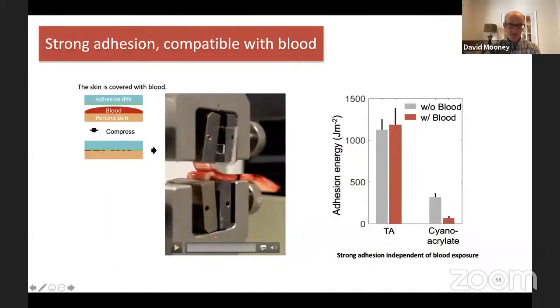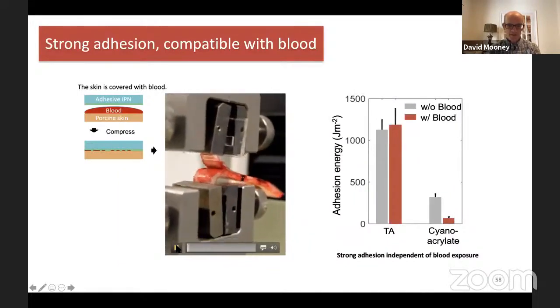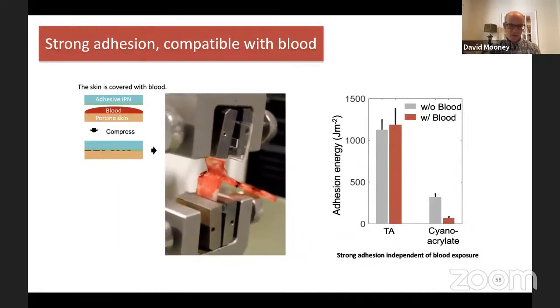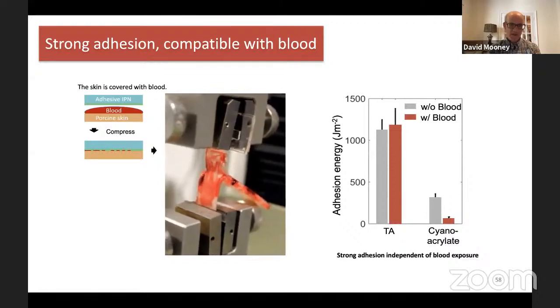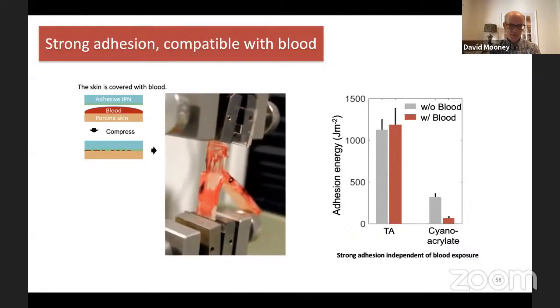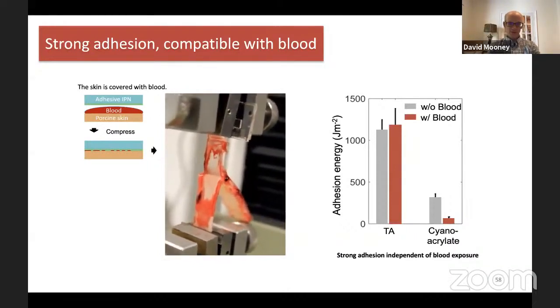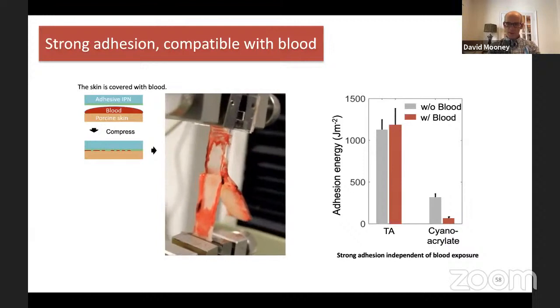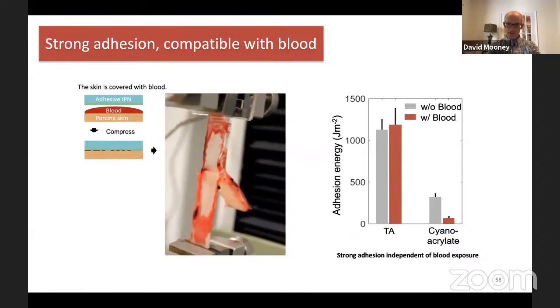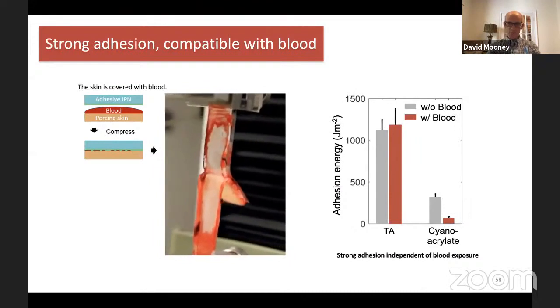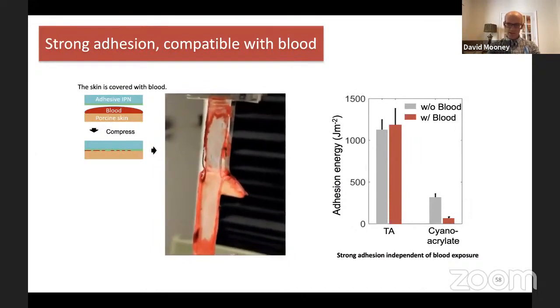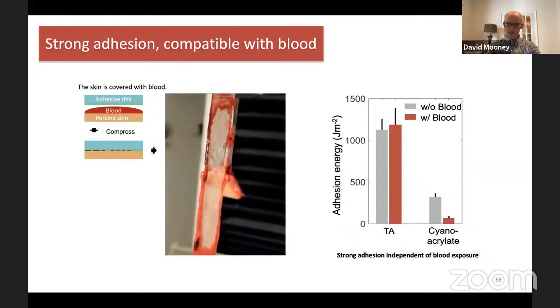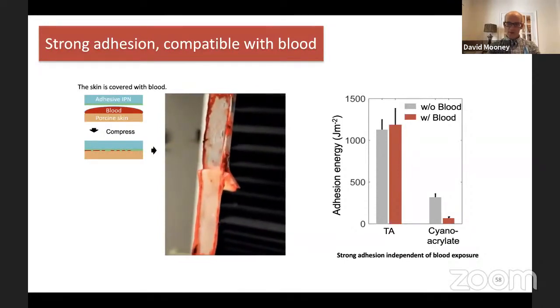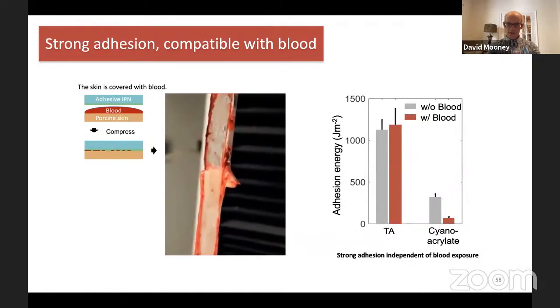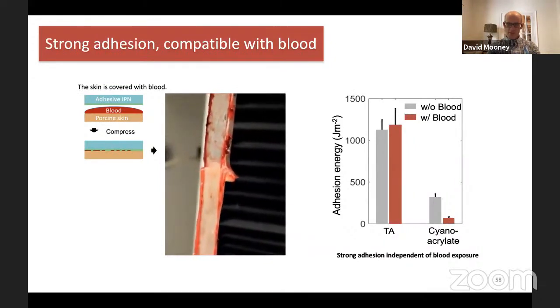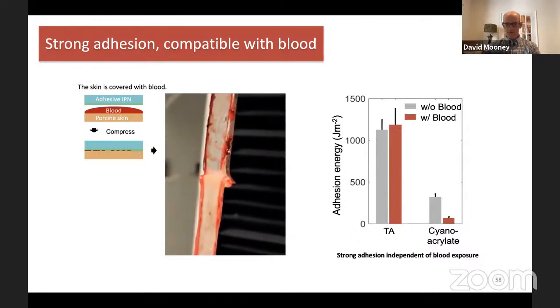Just to give you a sense of what adhesion looks like with the system, here's a simple experiment where we've now adhered one of these materials to porcine skin, and we did it in the exposure to blood to mimic a bloody surgical field, and you can appreciate we get very strong adhesion. What the numbers on the right are showing you is that the tough adhesive, or TA, dramatically outperforms cyanoacrylate in the dry state. And the cyanoacrylate is pretty much the state of the art adhesive in the medical field right now. And really importantly, in the context of a bloody wet environment, cyanoacrylate performance is dramatically reduced while the performance of this material is not.